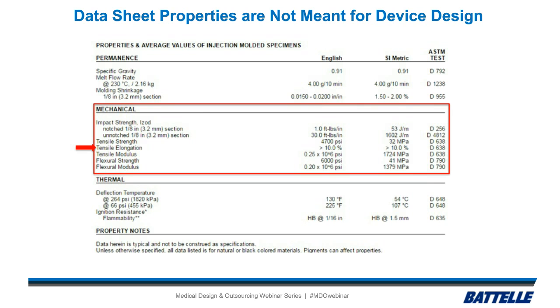And the third thing, the modulus. The modulus is calculated by taking stress and dividing by strain in a certain strain range, which is supposed to be linear, and that's called out in that ASTM D638. But they're not telling us exactly where they chose the strain, and basically we need to line up the modulus of the material with the strain range that we will be using it in. So we need to find out what we're straining the material to, and we need to use the stress strain curve and not just a single number to find out if it matches up with our design.